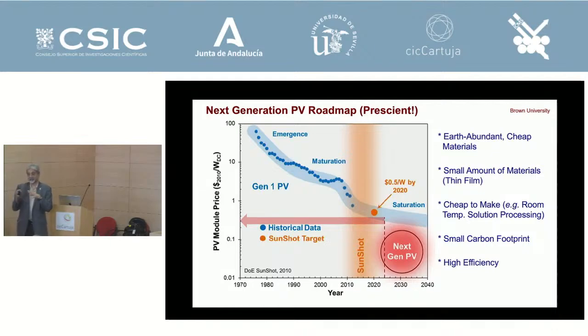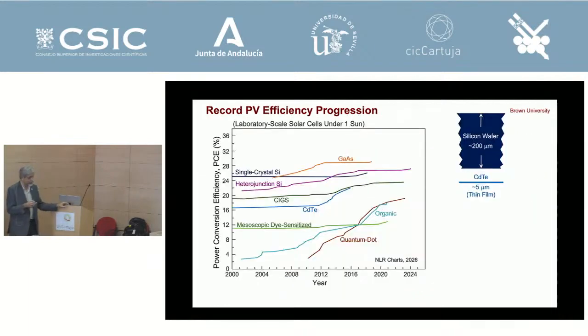And so the efficiency inherently is actually quite low, and therefore if you reduce the efficiency of the solar cells by new technology, which may be cheaper and use other materials, you have to use more real estate. So we cannot compromise on efficiency, right? So this is the chart of laboratory scale record efficiencies. And you can see silicon is basically flat. Gallium arsenide is one of the highest, but it's very expensive, typically used for satellites and things. And then this is heterojunction. And these are the emerging photovoltaics: dye-sensitized, organic, and quantum dot, and so on.